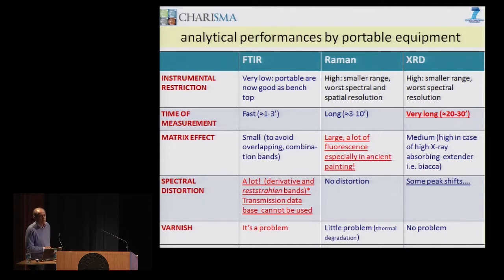The time of measurement is very important for MOLAB because you have to optimize the time and the intervention that you are carrying out in situ. You can see that FTIR is again at an advantage, requiring little time to carry out measurements. Raman is still acceptable, but X-ray diffraction is a disaster, because to carry out measurements by X-ray diffraction you need at least 20 minutes in the optimistic cases. But believe me, even the 30 minutes reported here is low. You need much more if you want to obtain a very good spectrum.